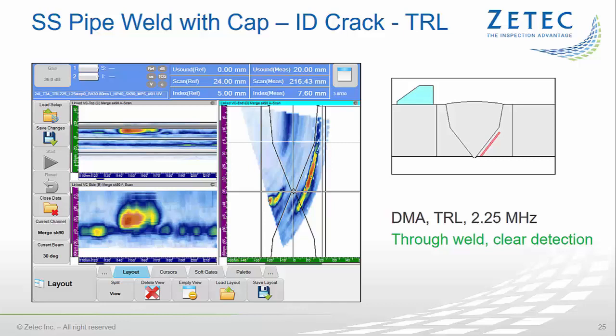This proves that the L-wave beam has propagated through the weld without too much attenuation or distortion. For this large crack, the signal-to-noise ratio was actually very similar to the result from the near-side examination, but it might be reduced for smaller ID cracks. This example clearly shows that the L-wave beams generated by well-designed DMA probes can reliably detect flaws through austenitic weld material. In this specific case, the data even allow for reliable length sizing.